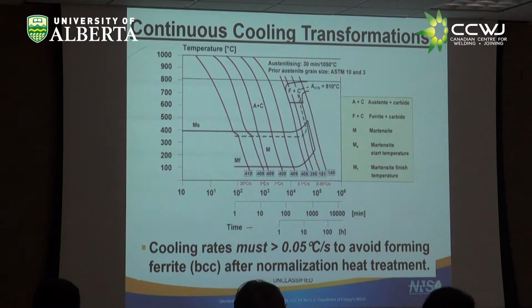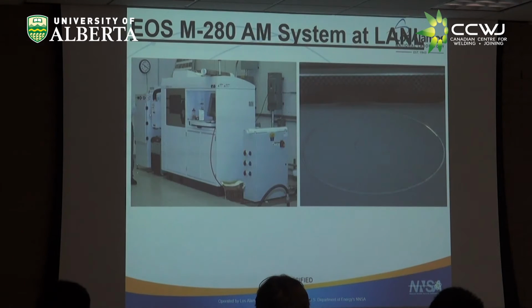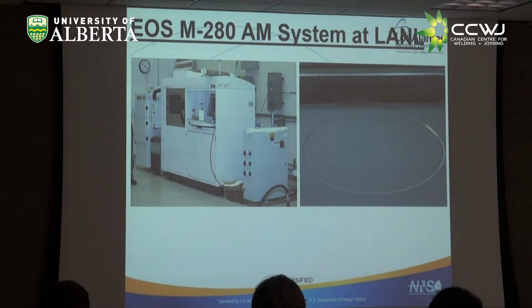We'll then go back and normally we'll temper that after heat treatment, and you can get it at cooling rates down to as slow as 0.05 degrees C per second to avoid forming the ferrite phase, which you normally wouldn't want. Remember this phase diagram, and remember this continuous cooling transformation diagram. We used an EOS M280, so it's referred to as a powder bed, as opposed to the company I work for, which is directed energy.